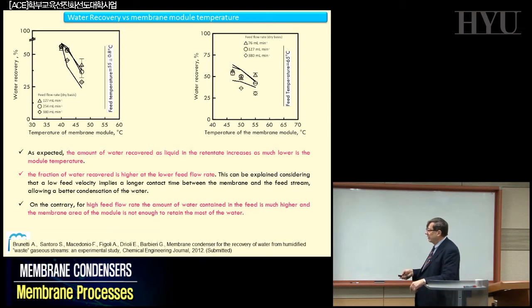On the contrary, for high feed flow rate, the amount of water contained in the feed is much higher, and the membrane area of the module is not enough to retain most of the water. So these are all experimental results which are quite consistent with the expectation, and they are quite consistent with the predictions that were done before, just in simulation.